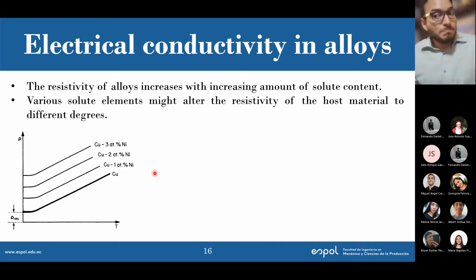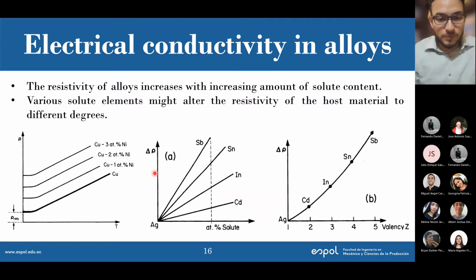And there is obviously an effect that different elements will alter the resistivity to different degrees. For example, let's go and show something. This is silver, okay? And I guess this is a better graph to explain. If I have silver and I put an element that has a valence of 2, like cadmium, then I can see that the resistivity already increases a bit. If I put indium, that has a valence of 3, for example, even higher resistivity.